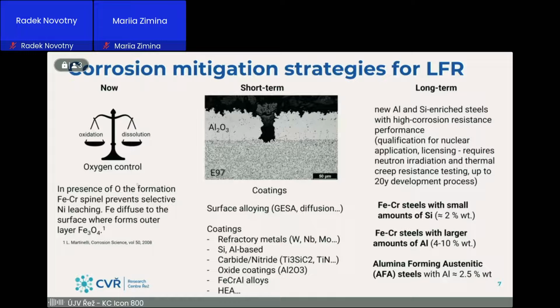some short-term solution can be applied, a coating on the internal reactor surfaces, but as with all coatings, there is a problem with what you will do with a defect in the coating. So when there is a defect, you have to rely on your oxygen control strategy, and that may develop some localized issues that are not critical for a reactor vessel, but there may be a problem for cladding because it's a very thin tube.